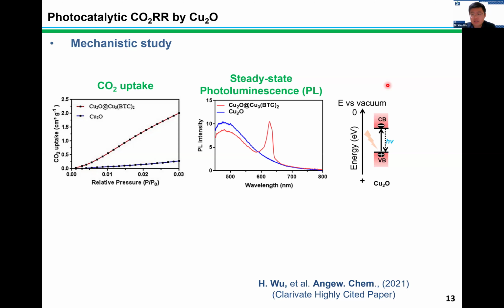So we plot the energy positions of copper MOF together with cuprous oxide, and we assume that the energetic electrons excited on the conduction band of cuprous oxide can transfer to the LUMO level of copper MOFs. When the electrons are transferred and there's no carbon dioxide in the system, the electrons on the LUMO level of copper MOF can recombine with the holes on the valence band of cuprous oxide and create a new emission signal. And here we would like to note that the energy difference between the LUMO level of copper MOF and the valence band of cuprous oxide perfectly matches the energy at 630 nanometers.